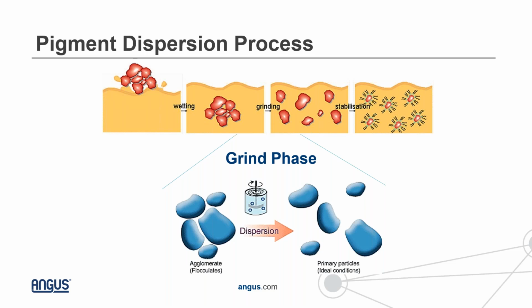But then you need to stabilize those, right? While you can get them to their primary particles by applying energy, in order to keep them as primary particles, you have to do some sort of surface functionalization. So that's the role of dispersants, where they essentially prevent the reagglomeration of those pigment particles.